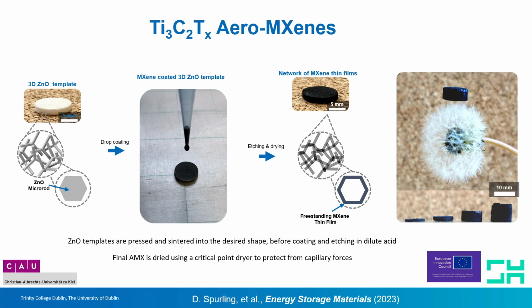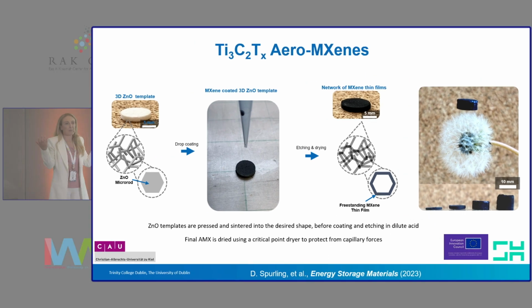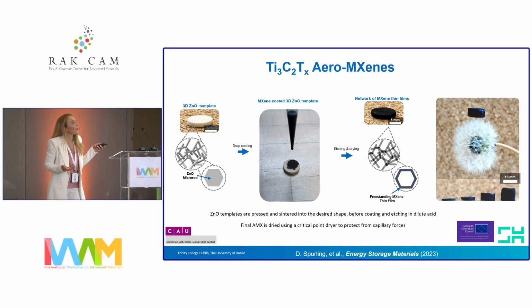What you do at the end is just etch away the zinc oxide, and you end up with hollow tubes made of MXenes. And these are 99% air. That's why we call them aero MXenes. They're super light. You can compress the pillars. And we like these devices.